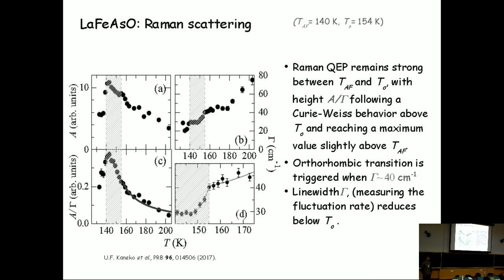Yeah, well, the fact that the transition temperatures are different doesn't mean that they are not driven by something else. What we think might be happening is that we have these nematic fluctuations that start growing and getting slower, and then it carries the structural fluctuations together with the nematic fluctuations, but the structural fluctuations are really heavy. They are connected to each other by strain, and then they don't want to keep fluctuating. So when they get slow enough, they trigger a structural phase transition that does not necessarily match the electronic phase transition. That's what I think.